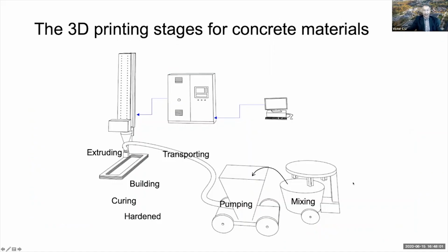3D printing of ECC is very similar to 3D printing of concrete, involving mixing, pumping, transporting through a hose to the nozzle where the material is extruded, the building of the structure, and the curing and hardening processes. However, unlike normal concrete, all these processes can become much more complex with ECC, mainly due to the fact that it contains fibers. For example, during the mixing process, the material must have good fiber dispersion so that they don't clump together.